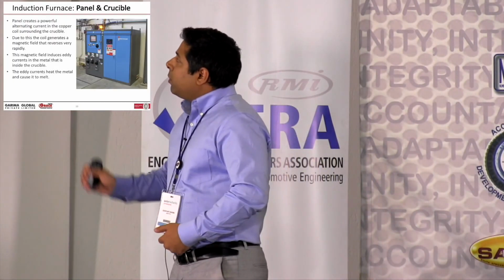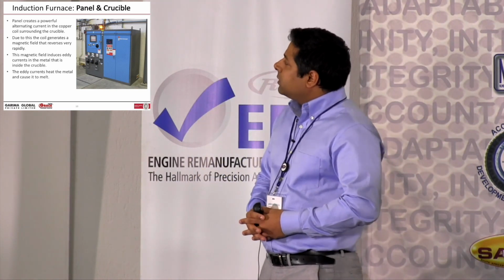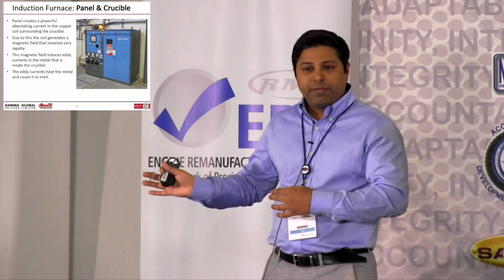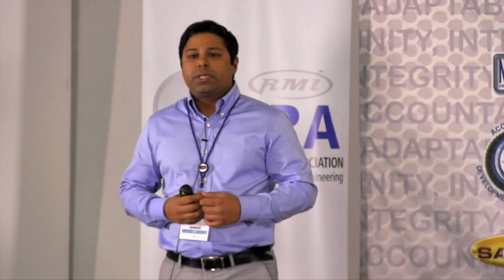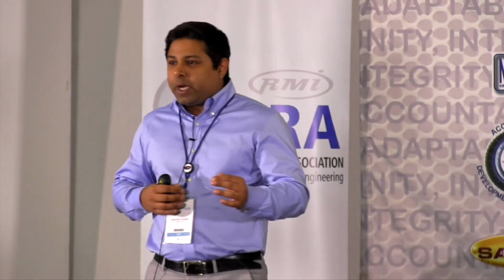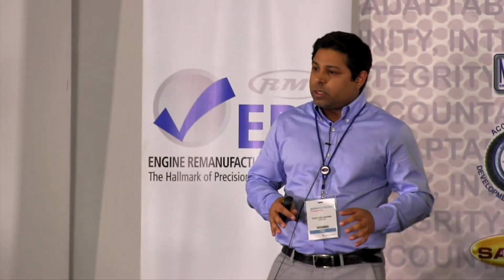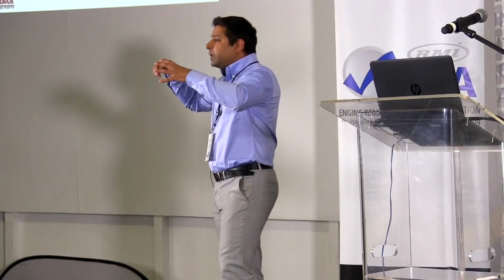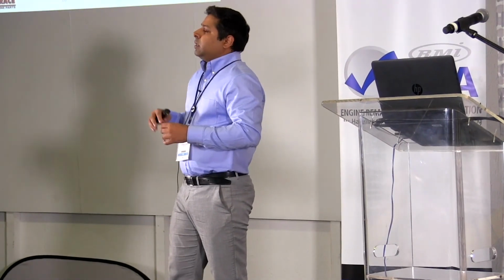So to talk about the induction melting part, you have this induction furnace which creates very high voltage and rapidly reversing electrical currents. These electrical currents cause eddy currents in the material that has been put inside the crucible. These rapidly reversing eddy currents cause heat to be generated within the molten metal, and then that heat causes the metal to melt.